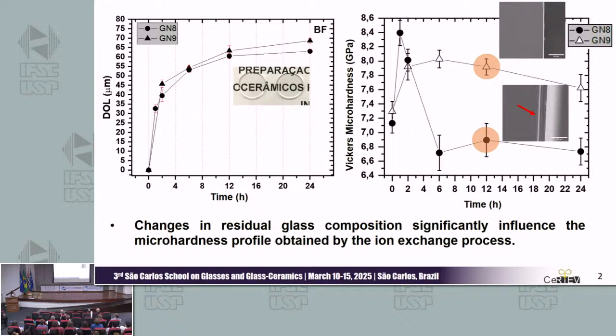Sorry. As you can see in the second graph, there is a great difference between the microhardness profiles in GN8 and GN9 glass ceramics. These changes are related to the slight difference in the residual glass composition of these glass ceramics, which influences the residual stress generated during the ion exchange process, as well as surface properties like thermal expansion coefficient and indentation resistance. If you are interested in this topic, I'd like to invite you to see more details in my poster during the poster session. So thank you.